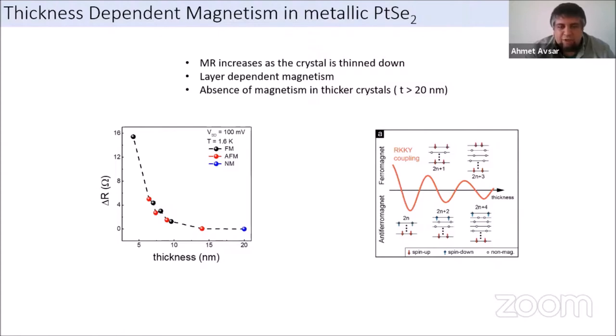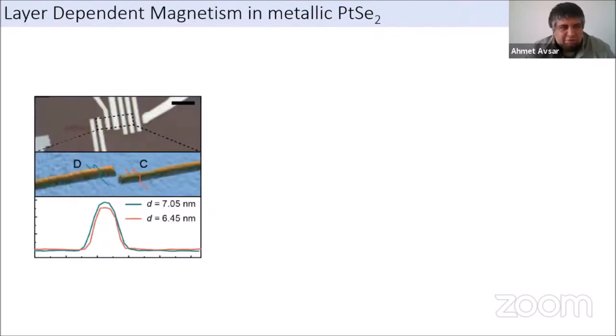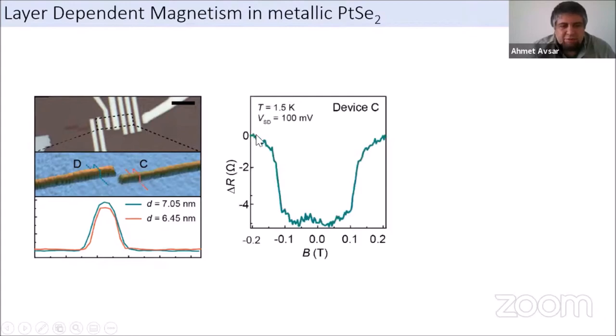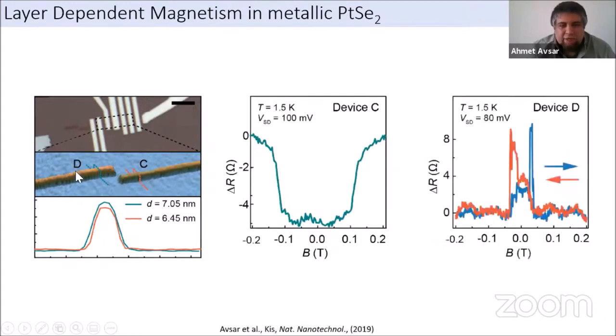And the question is, really, do we have layer dependent magnetism in this material? Especially our PhD student at that time, now he's a doctor, Alberto, he worked very hard to isolate these materials. And then what we were looking at is getting two materials next to each other, but one of them is just one layer thicker than the other one. And then we finally get these materials. These are two platinum diselenide ribbons with a thickness just varying by one layer. Okay, and if you measure the magnetic response in these devices, you have again this two plateau system. But if you measure the next device, then we do see this ferromagnetic type of response. So it looked like we had layer dependent magnetism by just changing one layer. The magnetic ordering is changing in here.